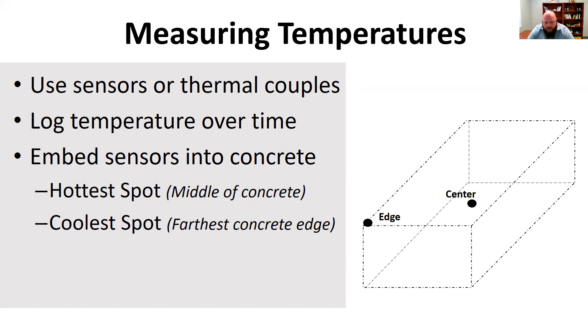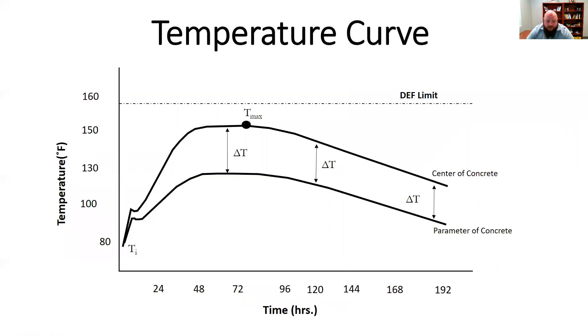You want to have sensors typically in the place that's going to be theoretically the hottest — usually the middle of the concrete — and then you want to find the coolest spot possible. If it's exposed to the environment, maybe right on the edge of the formwork, that may be the coolest spot. Those are kind of where people like to place the sensors.